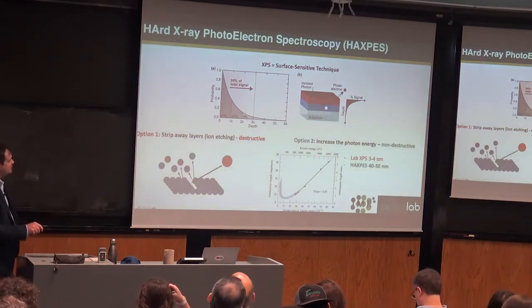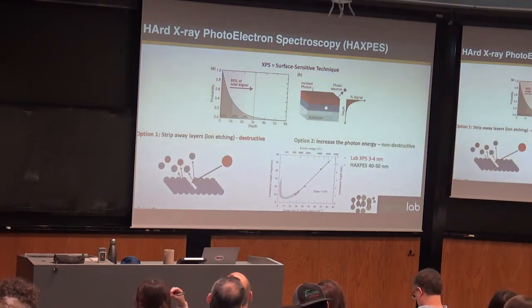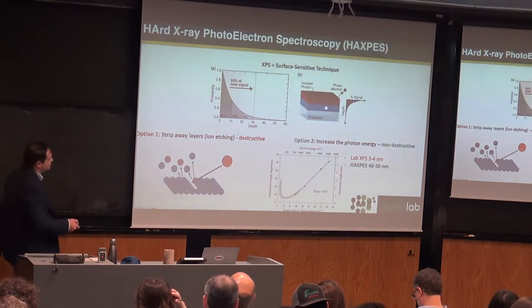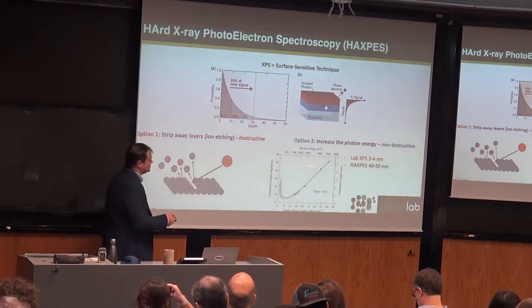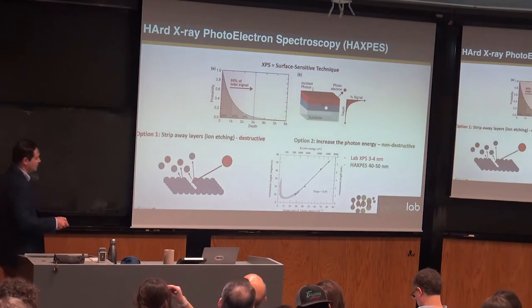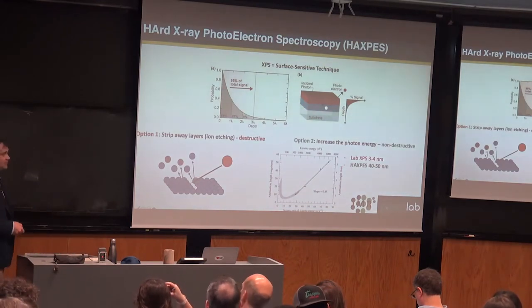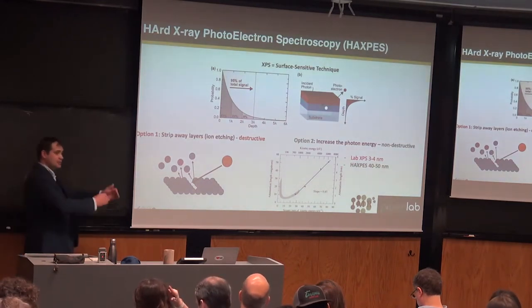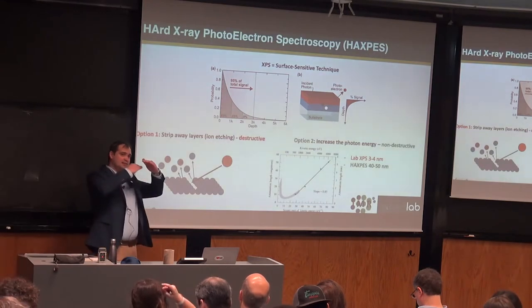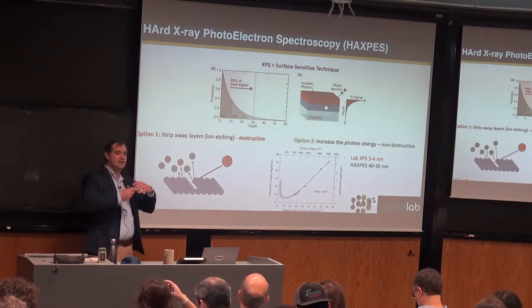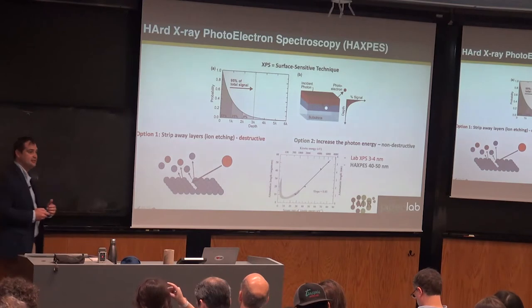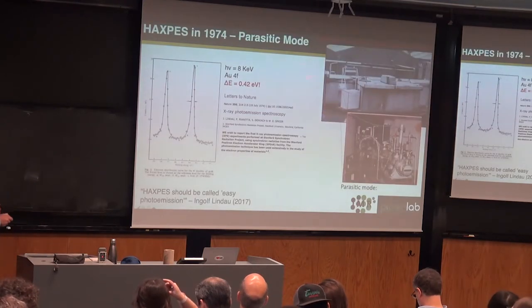So you can go from a case where the lab-based XPS you have here, for instance, will give you information within 3 to 4 nanometers, to where 95% of your signal could then be within 40 to 50 nanometers with HAXPES. If you're talking about thin film transistors, you're talking about stacks of 10 nanometers on 10 nanometers. These are meaningful dimensions. There's nothing new in the world.